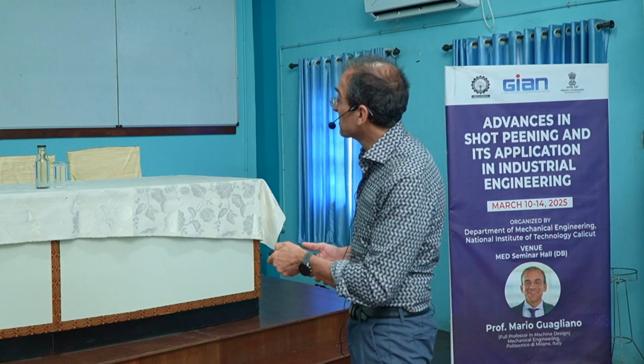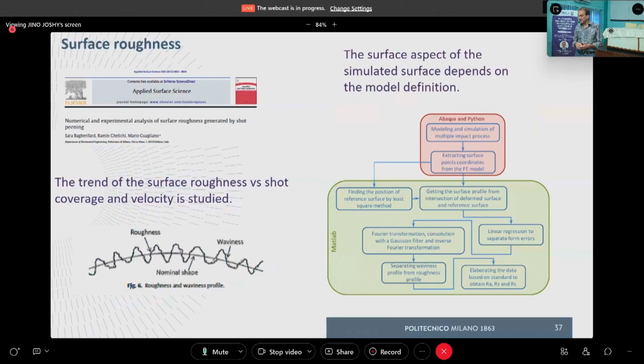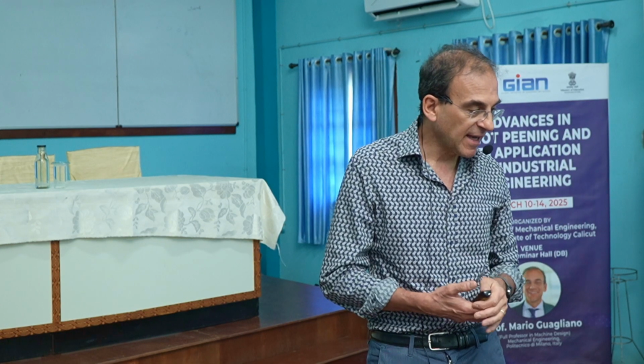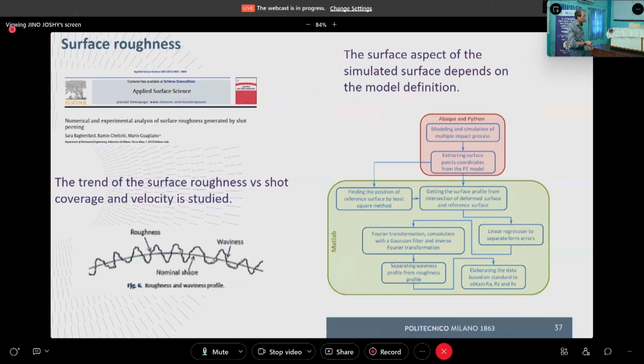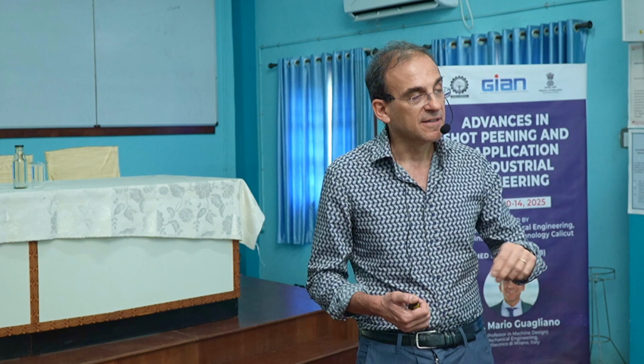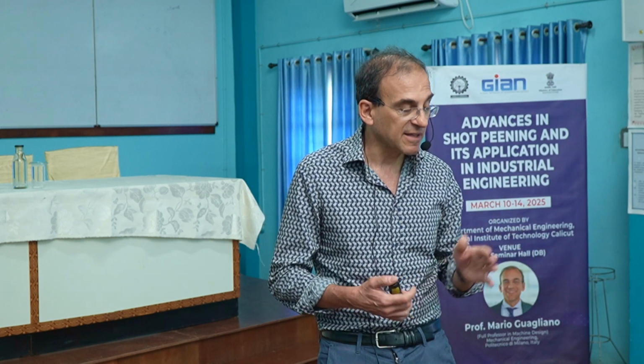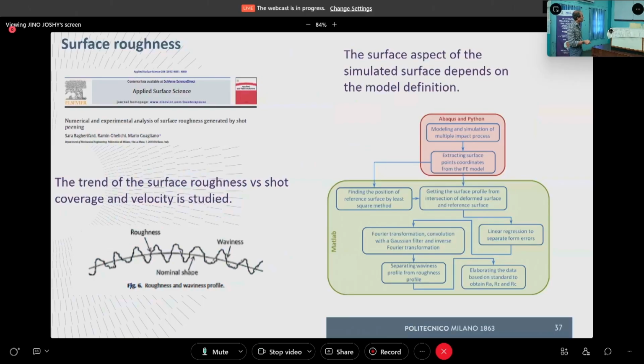And we developed this tool, let's say, that is based on Abaqus modeling and Abaqus simulation, finite element simulation, of multiple impacts. And when we talk tomorrow about simulation, we will see how we can do that. And then we are extracting the surface point coordinates from the FE model after deformation. So we are extracting just the surface, and we are treating this result as input of this MATLAB code, where finally, I don't want to go into all these points, but finally, what are we doing with this? We are somehow filtering the input in such a way that the noise caused by numerical calculation is somehow smoothened. And we are able in this way to separate what is waviness and what is roughness.